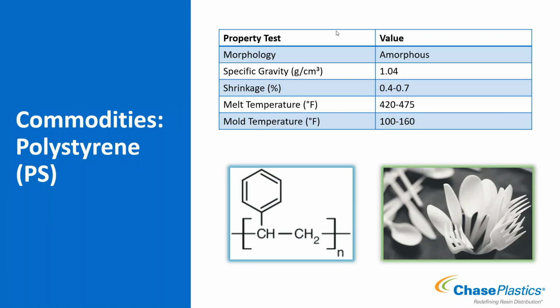These are going to sink if you were to take any of those knives, forks, what have you, and put them in the water, they're going to sink. Because it is an amorphous material, it shrinks less, so 0.4 to 0.7 compared to the 2%, which was the general range for your propylene and ethylene as semi-crystalline grades. And we're still in that 400-ish range for melt temperature, and your mold temperatures in the 100 to 160-ish range. Again, always consult the processing for the specific grade you're working with.